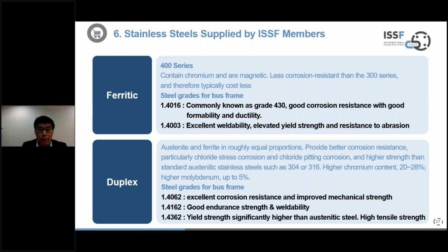And finally, we have duplex. Duplex, as I mentioned before, is a mixture of austenite and ferrite materials. It provides better corrosion resistance. Actually, it has the best corrosion resistance when you compare it to the other families, particularly in chloride stress corrosion and chloride pitting corrosion. So it has better performance when you compare it to 304 or 316. The grades that you can use and are actually already in use are 1.4062, 1.4162, and 1.4362. So these grades that I mentioned, they're already in use.